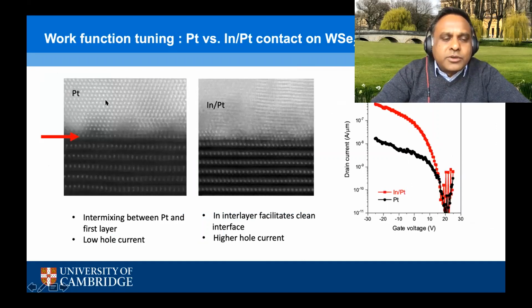In order to try to make good p-type characteristics, we've also looked at alloying the indium with platinum. These are again cross-sectional TEM analyses of pure platinum on multi-layered tungsten diselenide. What we find is that direct deposition of high work function metals like platinum causes damage at the interface. But if we buffer the platinum with a thin layer of indium, we're able to maintain this clean interface. And the electrical consequence of that is that we can get this p-type characteristic with In/Pt with a relatively high current.